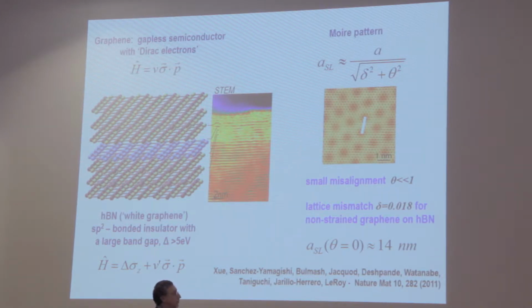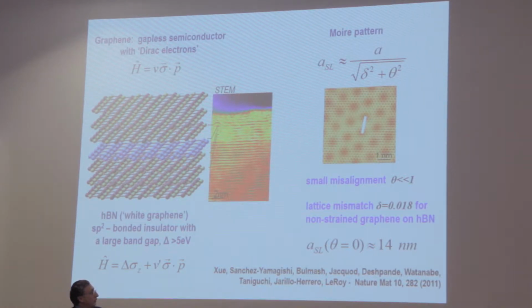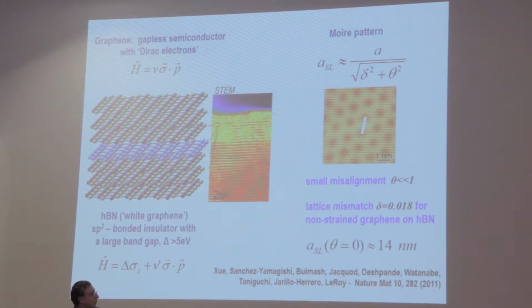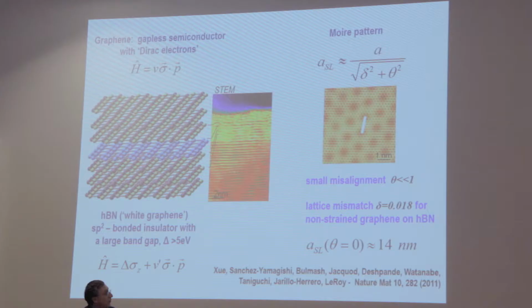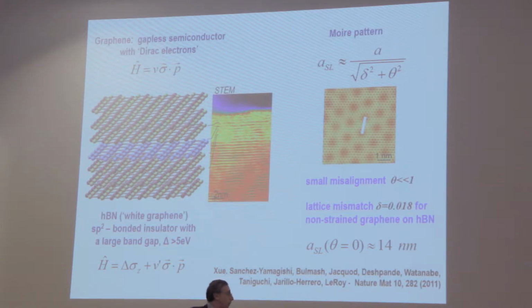And what has been mentioned in the previous talk is that the Moiré pattern is also a characteristic feature of heterostructures between graphene and boron nitride. And the parameters which matter here are the angle of the alignment between the graphene lattice and the lattice of boron nitride, and also the lattice mismatch, which is unavoidable here because the two lattice constants are slightly different. And this small lattice mismatch determines the longest period that the Moiré pattern can have in graphene heterostructures with boron nitride, which is about 14 nanometers.